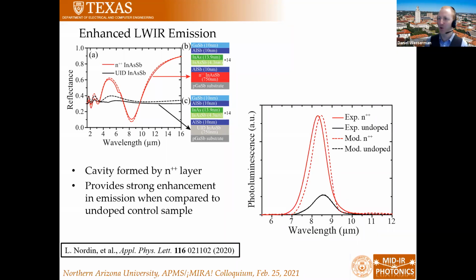But what's really, really cool, and the argument I always make, is that if you're someone who works in the near IR or visible, you have all of these amazing sources and detectors. You have such high efficiency lasers and such high efficiency detectors. And the problem with plasmonics, which has rightfully been panned over the last 10 years as not delivering on all of its promises, is that when you introduce metal into these amazing optoelectronic devices, it kills them. It kills the efficiency immediately, right? You take your 90% efficient device and you transfer all of that energy into a mode that is at best 30% efficient.